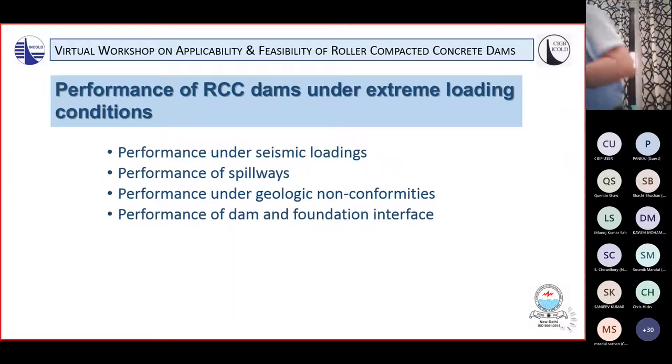To date, RCC dams have performed satisfactorily under seismic events. RCC dams that have overtopped, including cofferdams, have been satisfactory. The Câmara Dam in Brazil failed in 2004, resulting in 5 fatalities and extensive home and economic loss. The failure mode was attributed to erosion of weathered rock and at joint seams within the dam foundation. However, poor compaction at lift lines was noted on exposed surfaces.